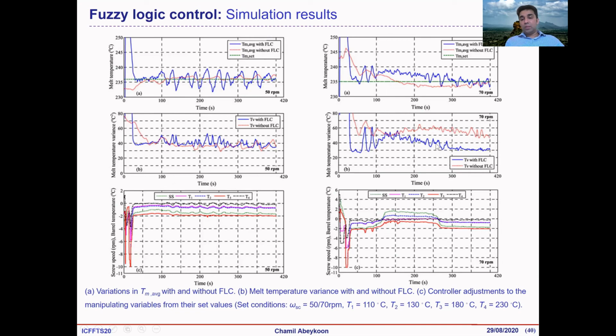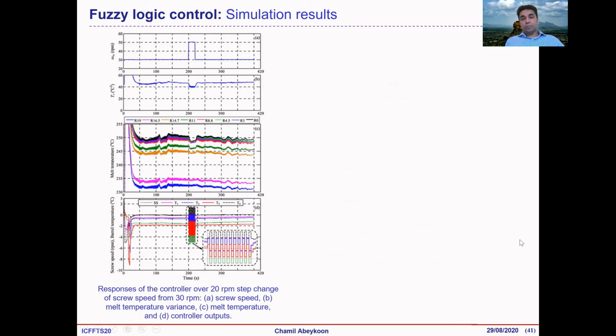This is the method without Fuzzylogic, and this is with the Fuzzylogic controller. This is 50 RPM, this is 70 RPM. And then after that, we introduce some disturbances to the process. Here we have introduced a 20 RPM disturbance to the input, the screw speed, and the controller can respond to that. And when we remove the disturbance, it can kick back to the normal process, trying to get back to the normal operating conditions.